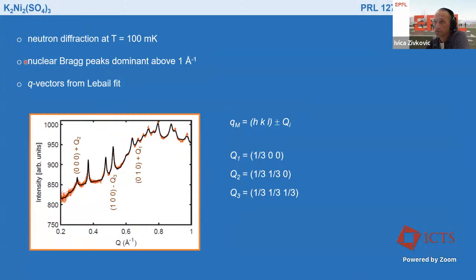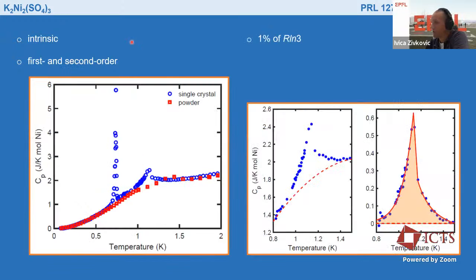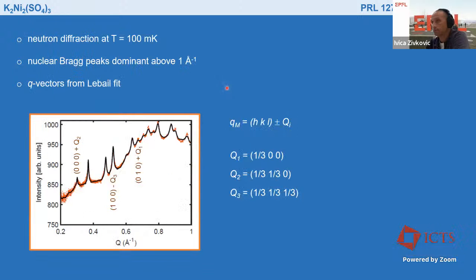And if you look at the neutron diffraction at a low temperature, so this is well below these features, 100 millikelvin, you can see a series of peaks appearing below 1 inverse angstrom. Everything above is dominated by phonons, by nuclear Bragg peaks. Although one cannot properly refine this structure, just extracting the position of the peaks and the q-vectors from the Le Bail fit indicates that we are not talking about a trivial one.